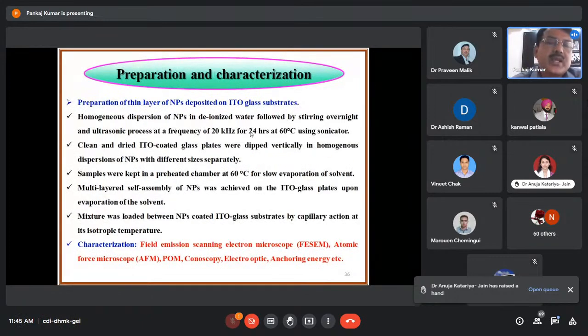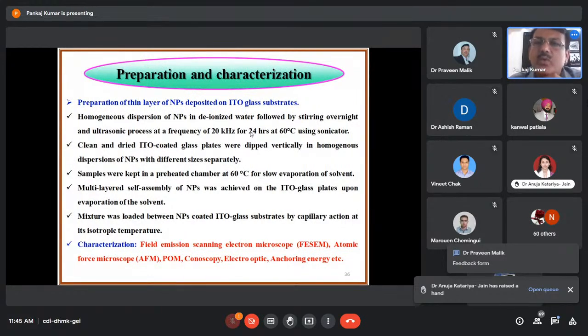So, preparation of a thin layer of nanoparticles deposited on ITO glass substrates. Homogeneous dispersion of nanoparticles in deionized water, followed by stirring overnight and an ultrasonic process at a frequency of 20 kHz for 24 hours at 60 degrees C using a sonicator. Clean and dried ITO coated glass plates were dipped vertically in the homogeneous dispersion of nanoparticles of different sizes, separately.